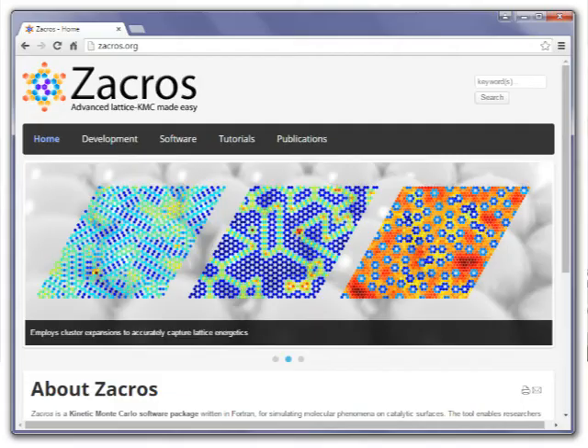We used quantum chemistry to study the reaction mechanism for different gold nanoclusters, and then estimated the catalytic activity using our kinetic Monte Carlo software ZACROS. Our studies show that defects in the support materials strongly influence activity, but also the size of the nanocluster is very important.